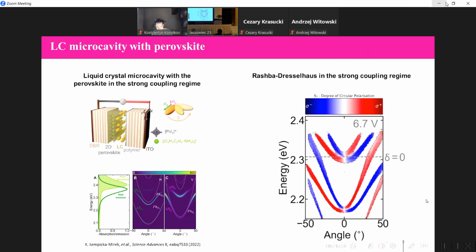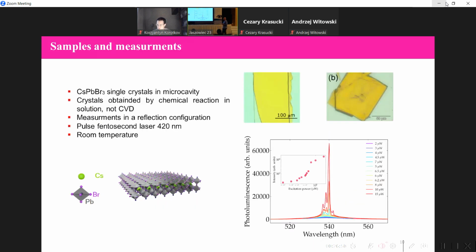We can make the microcavity with both perovskite and liquid crystal. In this case, for the two-dimensional perovskite, we obtain polaritons which have this spin-orbit coupling. But this is the case in these two-dimensional perovskites, and just to remember, they cannot host condensation at room temperature. So we obtained another crystal, just the cesium lead bromide single crystal, in the microcavity.